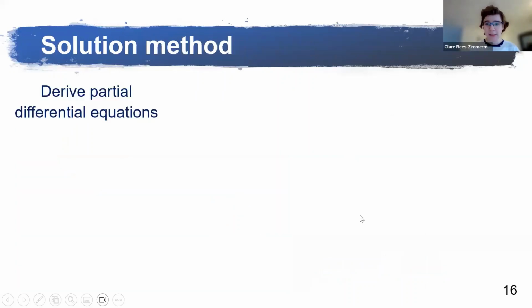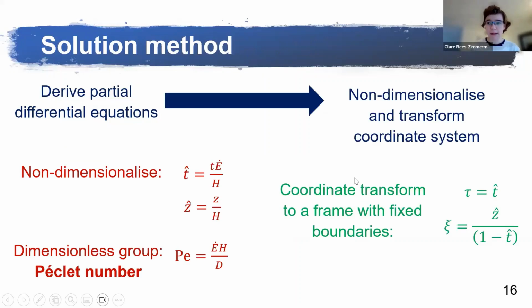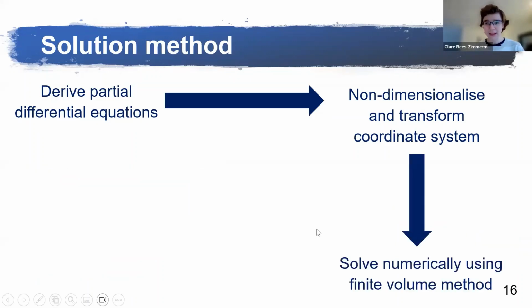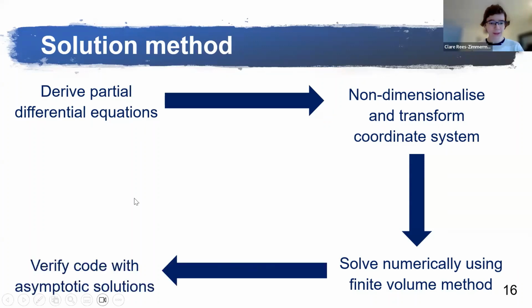So having derived some PDEs, I non-dimensionalize them, giving me dimensionless time and dimensionless space, and a dimensionless group for each particle type. That's the Peclet number. I then transform the coordinate system. That's because in the non-transformed system, the top surface is descending due to evaporation, and that's problematic for a numerical solution because the boundary condition is a moving boundary. I therefore use a coordinate transform to a frame with fixed boundaries, giving me new coordinates of tau and xi. I solve the resulting equations numerically using a finite volume method because this naturally conserves particles. And I finally verified the code with asymptotic solutions, which I'll show you in a bit.